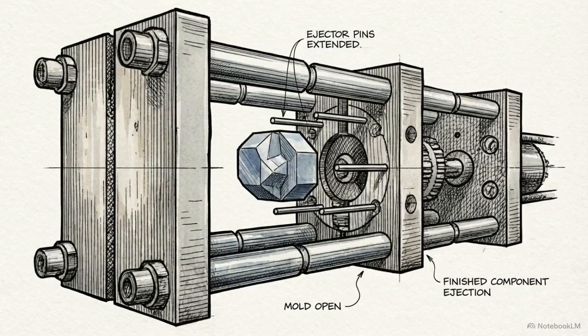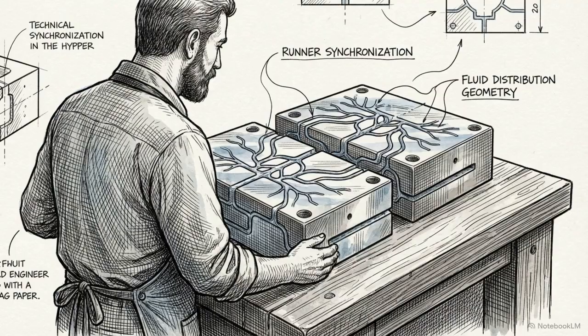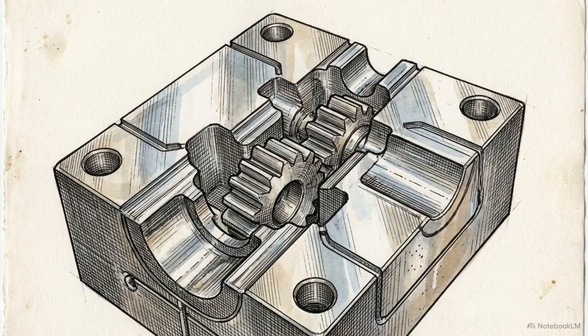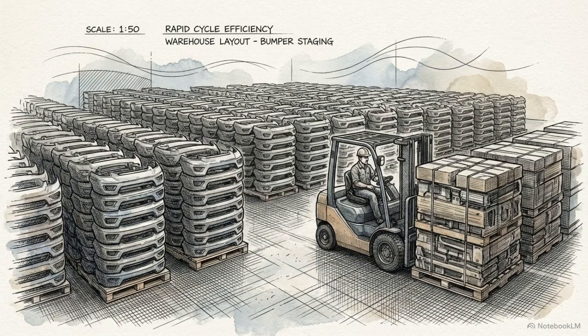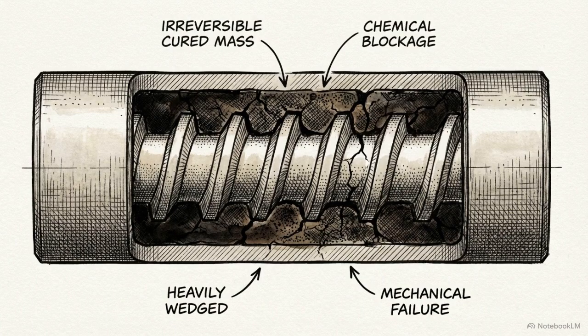Finally, in step 4, the mold opens and the internal mechanical ejection system fires, pushing the solidified, net-shaped part off the mold core. Engineering this level of continuous synchronization, from the complex runner geometries to the high-tonnage molds, requires immense upfront capital. A single steel tool can easily cost hundreds of thousands of dollars. Despite these tooling costs, the rapid, overlapping cycle times make injection molding a highly viable method for mass-producing millions of identical parts. This entire continuous system, however, is useless for thermosets.